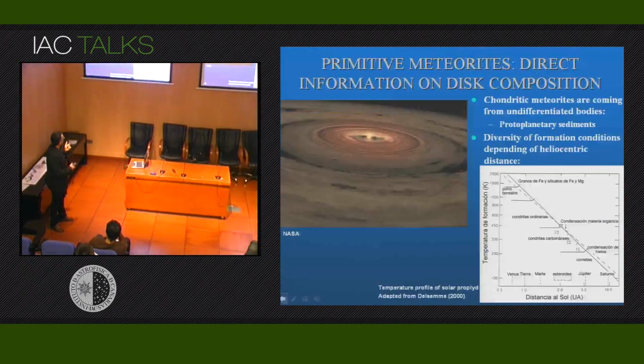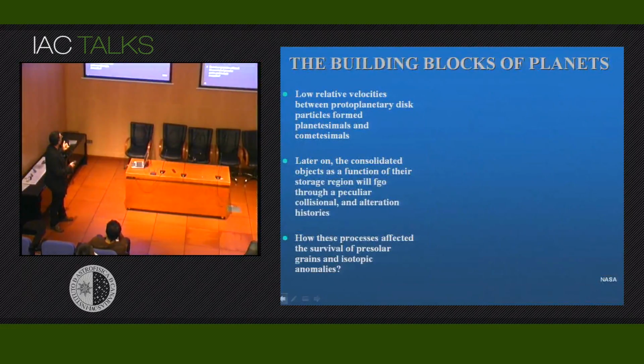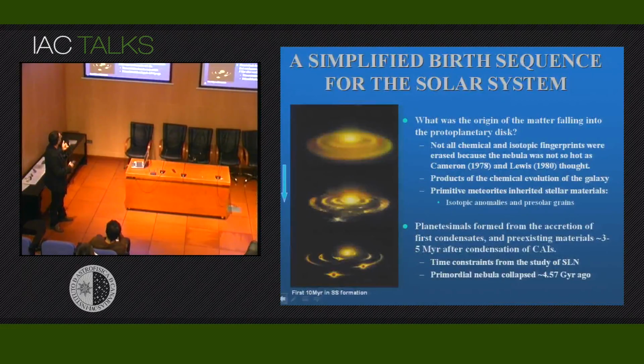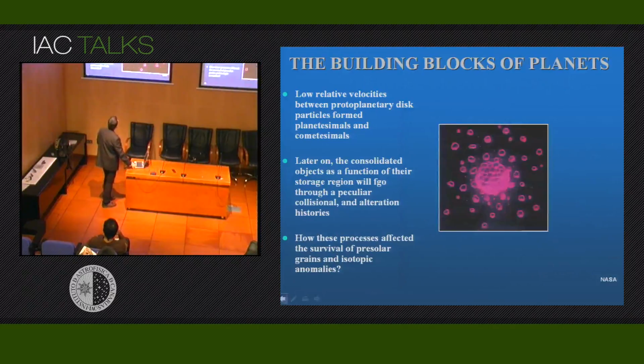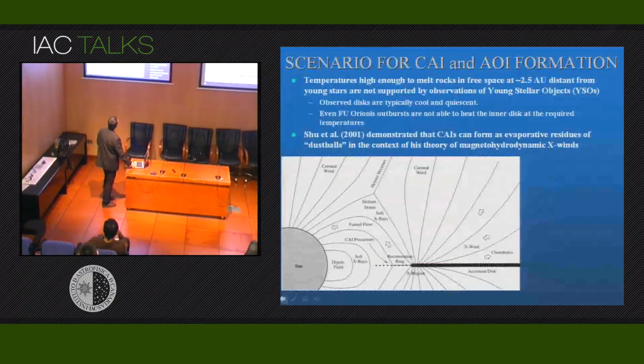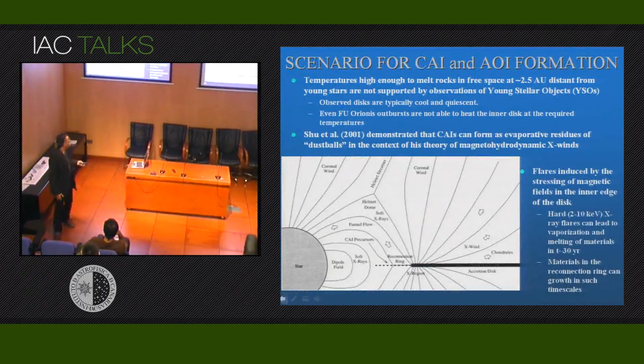So in this scenario, the flares that were induced by the stretching of magnetic fields in the inner part of the protoplanetary disk would be producing these X-ray flares that are able to vaporize most of the materials that were forming these clumps of dust. It means that the condensates probably were also not only calcium aluminium, but also magnesium, silicon, and other materials, but as a consequence of this reheating, most of these materials were vaporized with time.